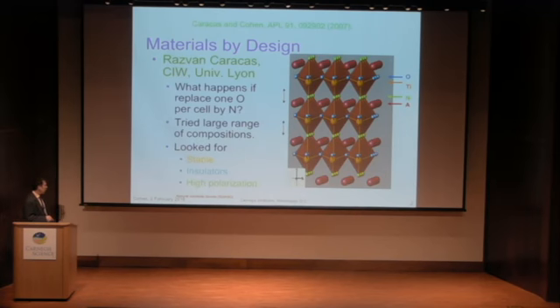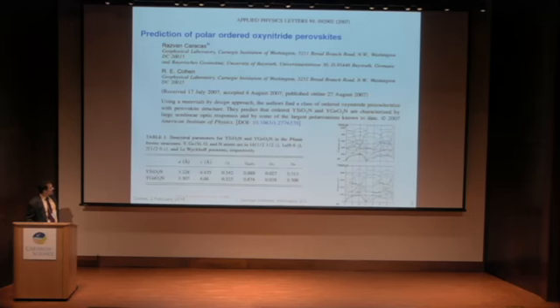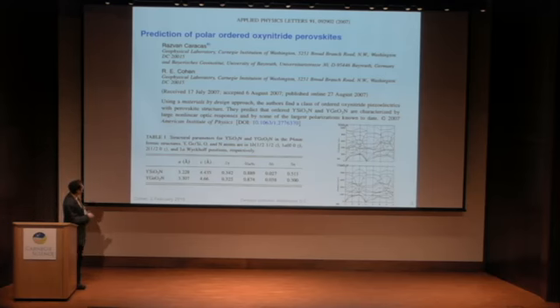I guess it's Si2N2O. But it has a mineral name since it's found in nature, sinoite. But generally, there's been a large effort in the materials world to make oxynitrides for a lot of reasons over decades, but none of them, well, except with some recent exceptions that I'll show you, have really been polar or possibly ferroelectric. But anyway, at the time that we did this work, there were none that were known to be polar or ferroelectric. We came out with two that seemed to be very promising, yttrium silicon oxynitride and yttrium germanium oxynitride. And they both had strong high C/A ratios.